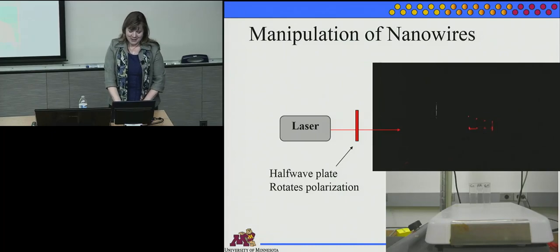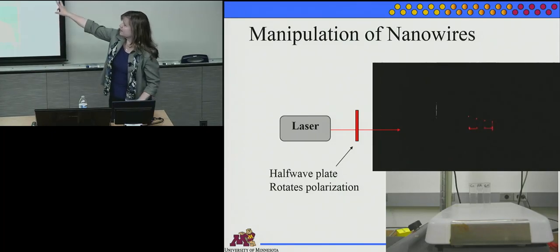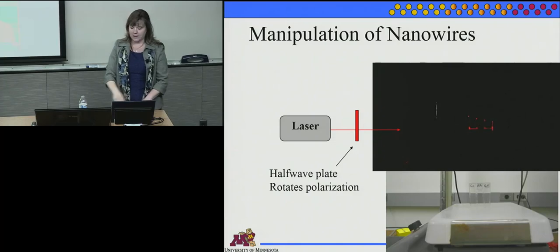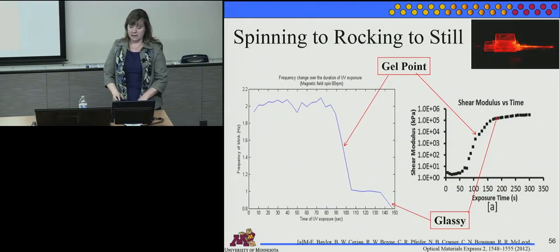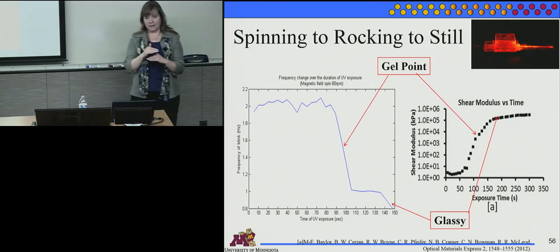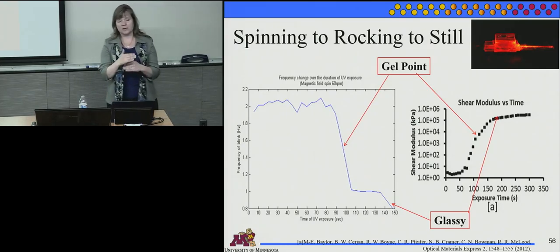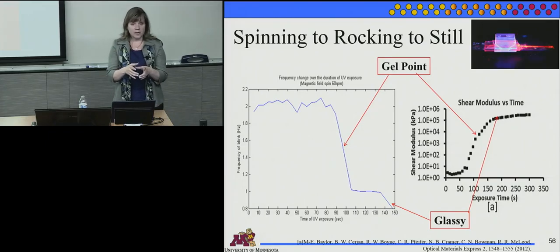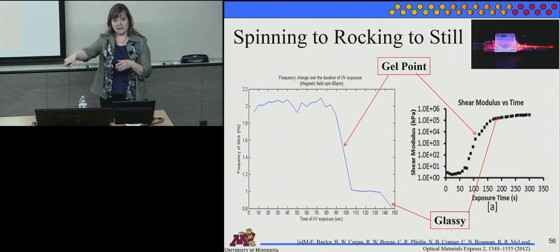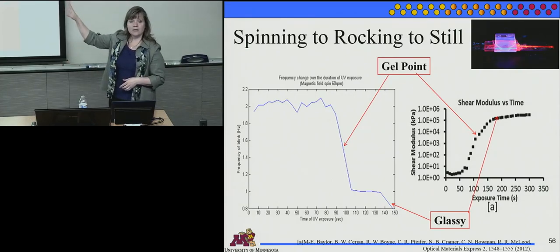All right, so that's what you're seeing in this movie: there's some vials with nanowires and they're spinning, and I've got a laser pointing through there. So let's go to the next movie, which is more interesting. This is actually 2 glass slides that have a UV curing polymer. So actually they're quartz slides. With UV curing polymer, we're shining the laser through, and we have it on a stir plate like this. And then we shine the UV light on.